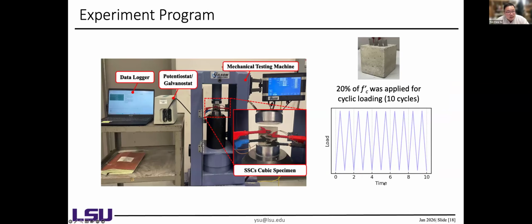So we also want to measure the self-sensing property, of course, and this is the configuration of our setup, and we use the four-probe method to avoid the bad signal, and we apply this 20% of the f'c to our sample, and for this cyclic loading for 10 cycles.